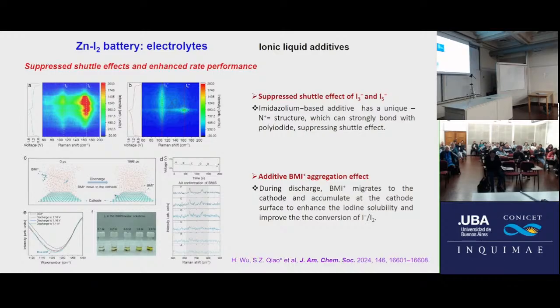Okay, why? If we use this additive, imidazolium, we can prevent the shuttle effect because this molecule has this structure. This structure has a nitrogen plus. It can bond the polyiodide, I3- and I5-. For this reason, we don't want to give the detail.